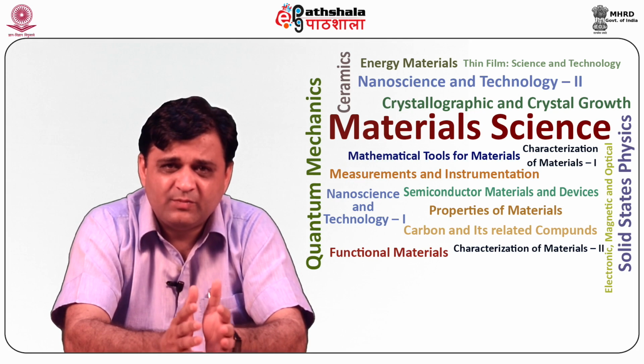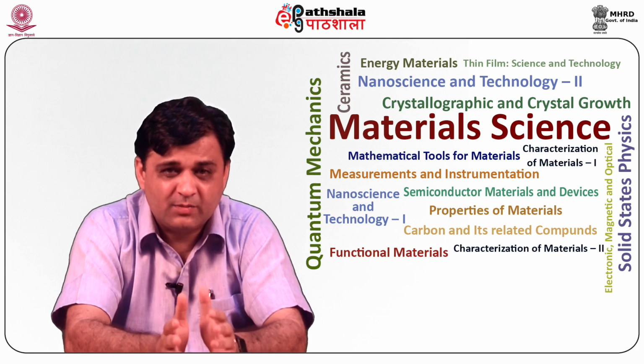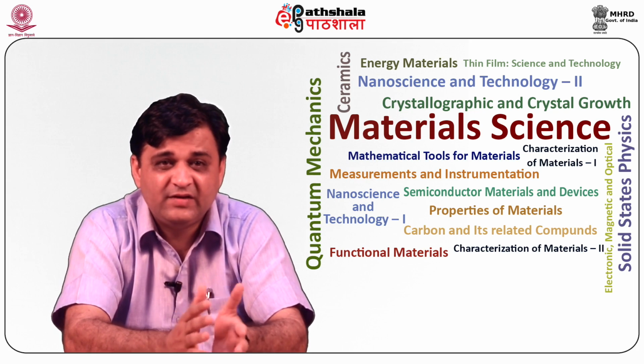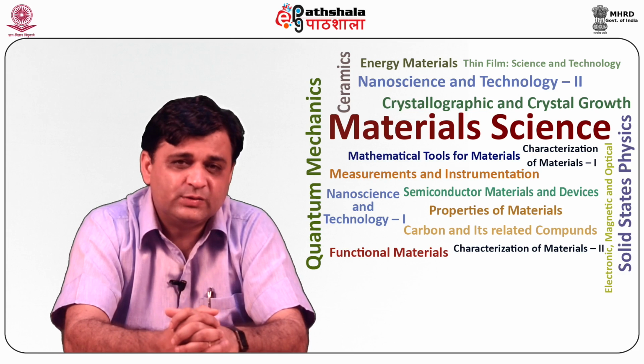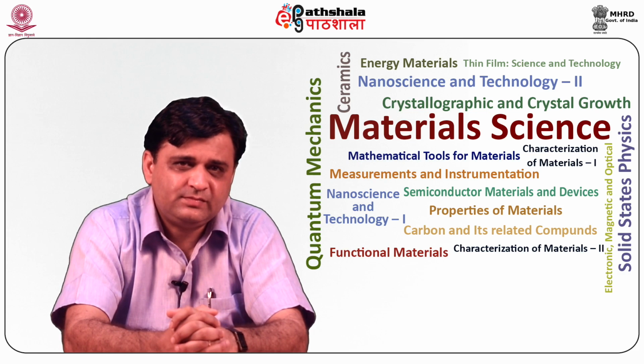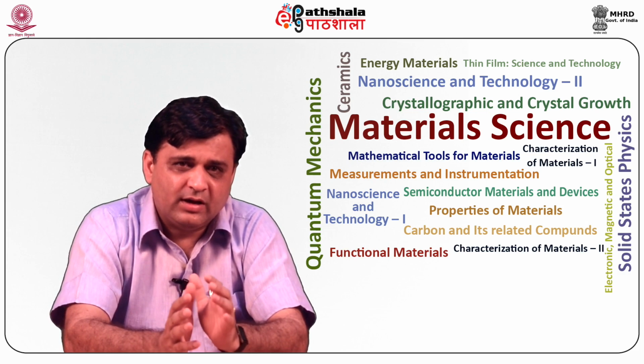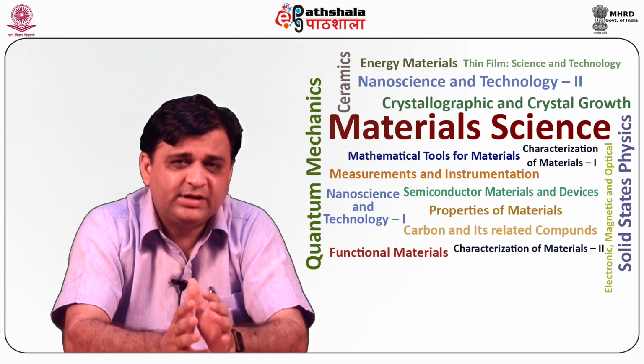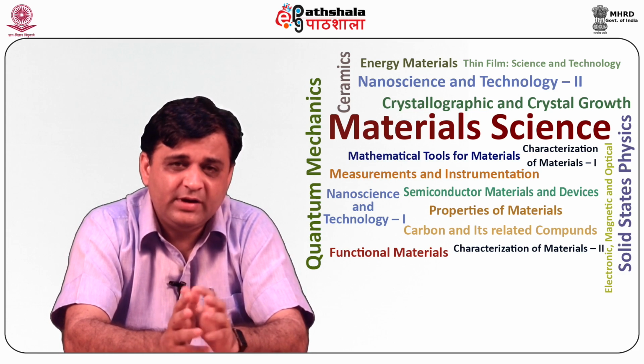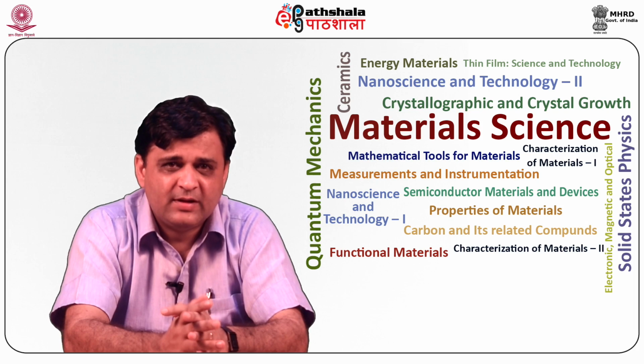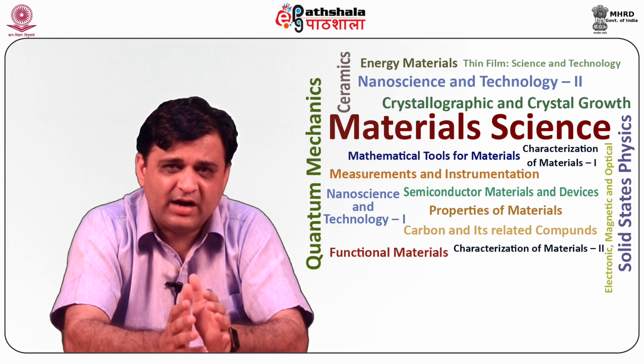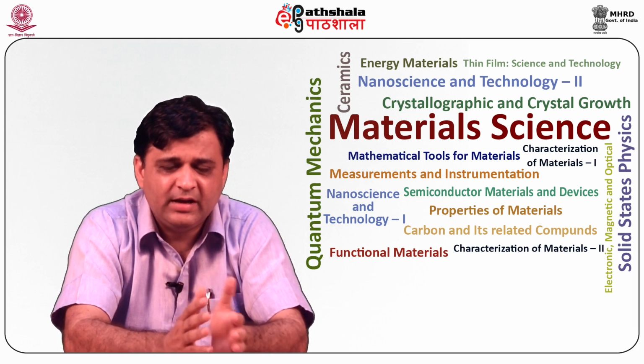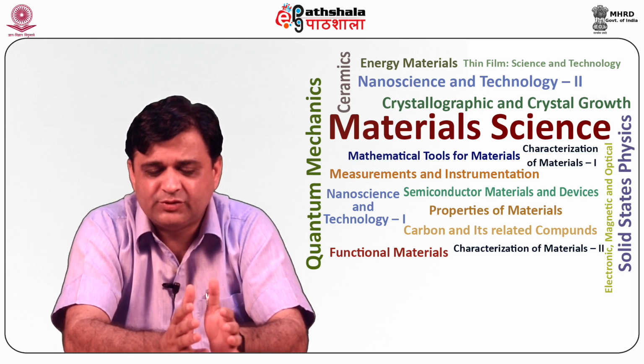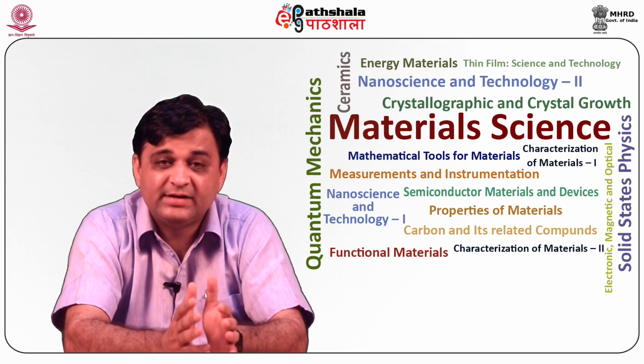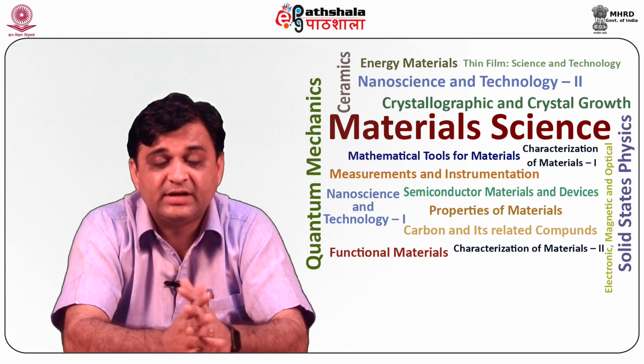In some cases, poor electron density contrast between two layers of hydrocarbons or organic samples makes it difficult for X-rays to distinguish the interface. But in neutron reflectivity we have the option to enhance the scattering contrast by chemically replacing hydrogen with deuterium in one system. For neutrons, hydrogen and deuterium then provide sufficiently good contrast, and we can get a really good reflectivity.